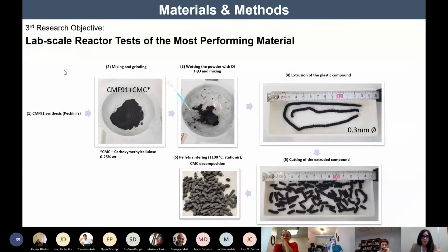We prepared the pellets by mixing the CMF91 powder with different amounts of carboxymethyl cellulose, and wetting the powder with a small amount of water so that we could create a plastic compound that could be easily extruded through a die of 0.3 millimeters. The extruded compound was cut into pieces of 1 centimeter length, and the pellets were sintered at 1100 degrees C under static air in order to decompose the carboxymethyl cellulose.